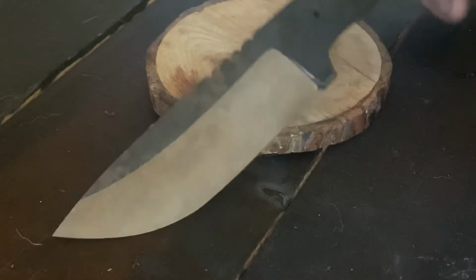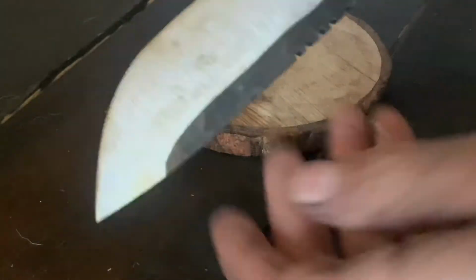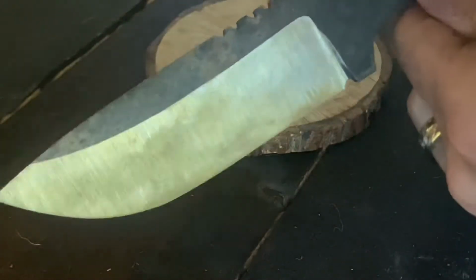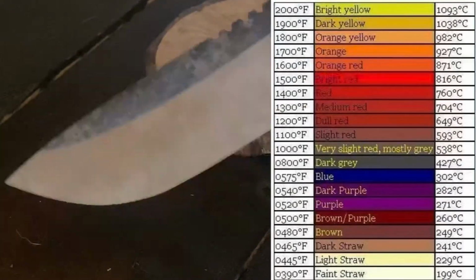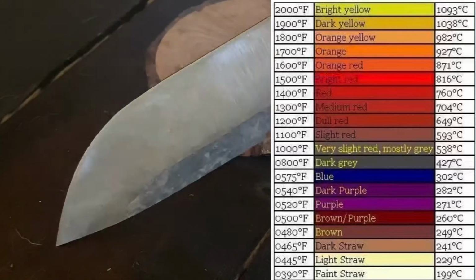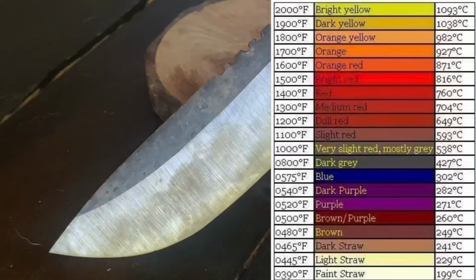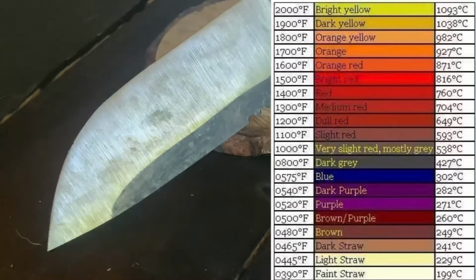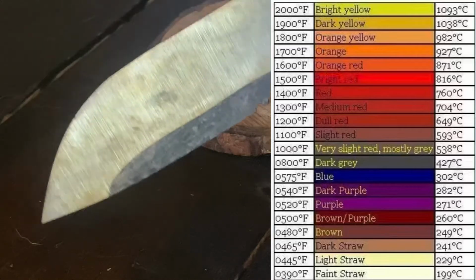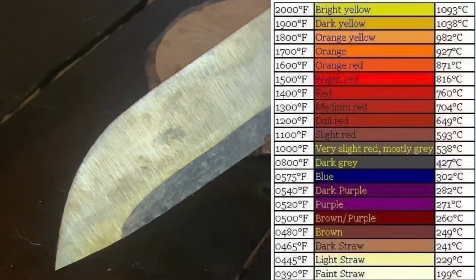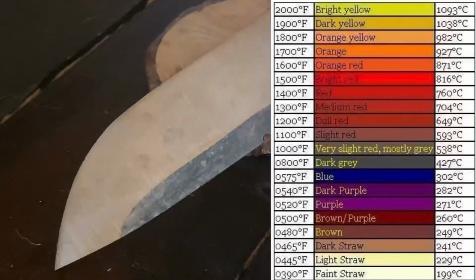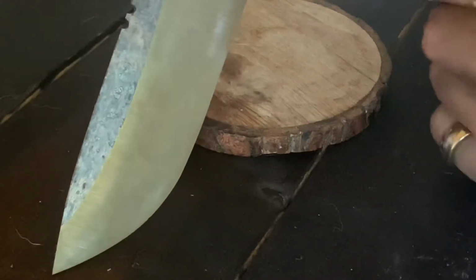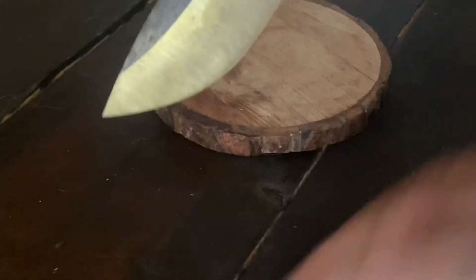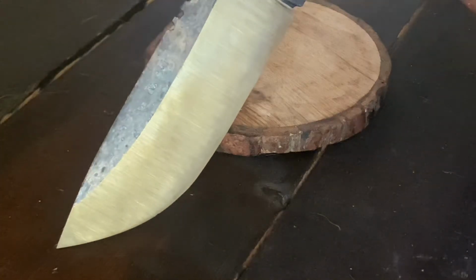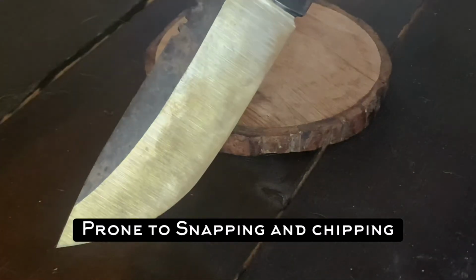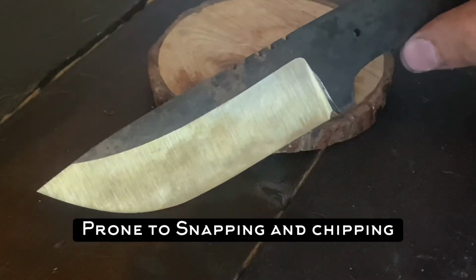All right, now what you have is a hardened, tempered blade. It's a little bit dirty, as you can see, but what you want is that straw color. In fact, this is a little bit too light. So what I'm going to do is put it back in probably for 425 degrees for about an hour. But what you want is a light straw color so that you know that the blade is tempered, and let it soak like that for about an hour once you've reached it. So it's important to make sure that's done. Otherwise, if you don't temper the blade, you will have a very brittle blade that is very prone to snapping. So it will not be considered a functional blade until you do so.